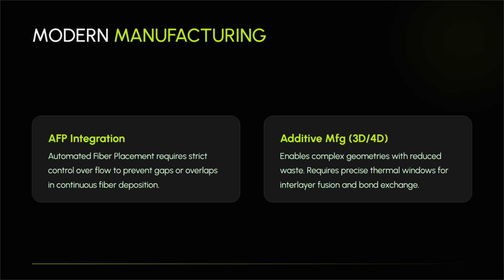On the other hand, additive manufacturing, such as 3D and 4D printing, opens up incredible opportunities for fabricating complex aerospace geometries with minimal material waste. However, successful printing requires an exceptionally precise thermal window. The temperature must be high enough to allow rapid bond exchange across the printed layers to ensure strong interlayer adhesion, but low enough to maintain structural stability during deposition.